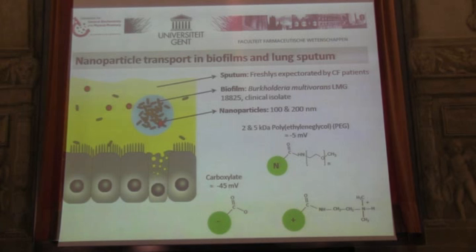The bacterial biofilm, it's indicated here, it's a very dense cluster of bacteria, and they also secrete an exopolysaccharide matrix, a slimy matrix that protects them from the environment. So the combination of this exopolysaccharide matrix and the dense cluster that they are forming makes them very hard to be killed by classic antibiotic therapy. So what we would like to do is to develop a nanomedicine formulation that can penetrate through the sticky mucus, that can penetrate into these dense clusters and give them a sudden release of high doses of antibiotics.